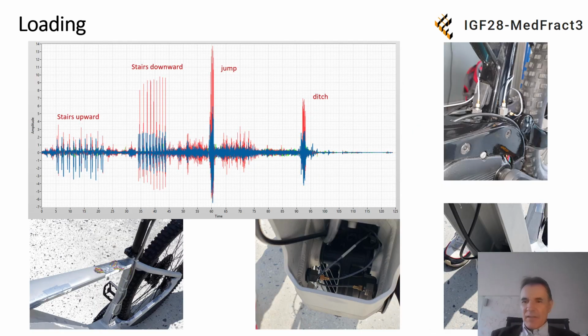For the assessment of fatigue lifetime, it's necessary to determine the appropriate loading process. Here is documented the process of how we try to determine this important loading state. For the e-bike, 4 important loading states were determined: upward stairs, downward, then jump, and overcome the ditch. During this operation, the operational state was measured by accelerometers, which are situated inside the tube of this e-bicycle frame, and also by strain gauges, which are situated on the tube between the rear and side tube.